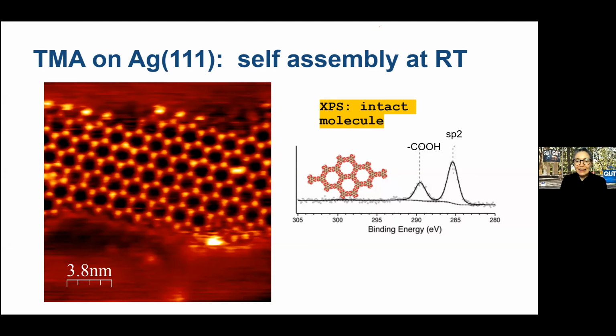The schematic at left here shows you the combinations of bonding that are involved in these structures, where when we have discrete pinwheels, we actually identify that there is very likely a cyclic hydrogen bonding going on in the portion of the molecules which still retain their carboxylic groups, and that there is a cyclic bonding of the carboxylates around the bright features in the other part of the molecule.